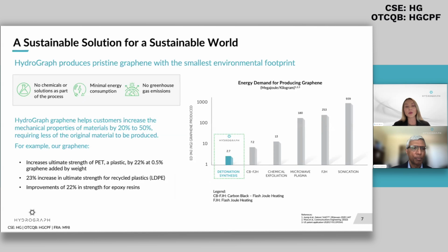the environment. We can so greatly improve the strength of materials that you can then reduce the amount of legacy material that you're using on average by as much as you're increasing the strength, which for us is often double-digit performance improvements. To give some examples, we can increase the ultimate strength of PET, which is a plastic, 22%. So you could use 22% less PET, which is a carbon-intensive product, 23% for low-density polyethylene, and 22% for epoxies. This would ring true for concrete. This can extend the life of lubricants, and many more examples.